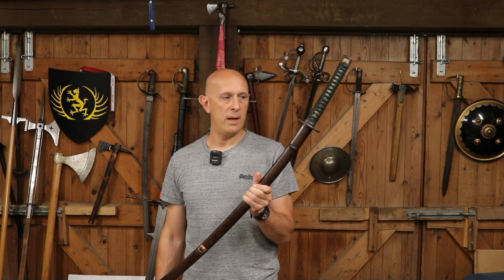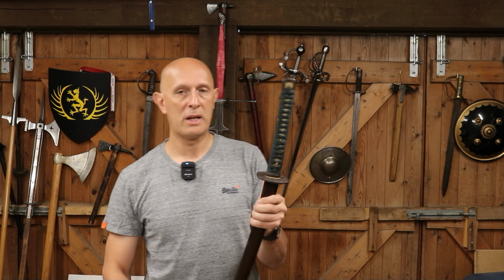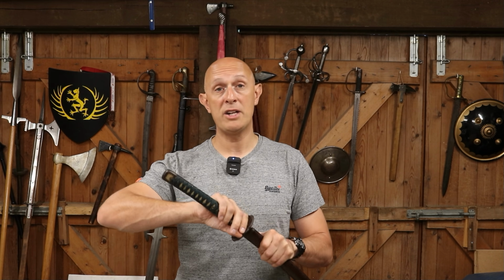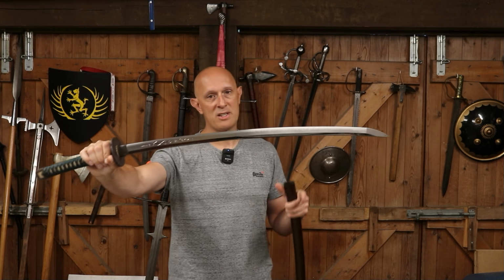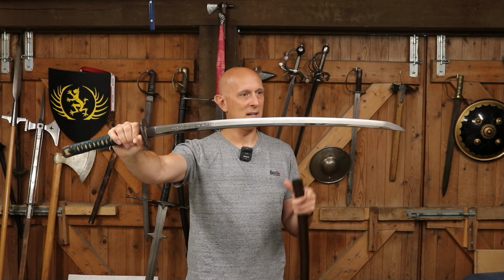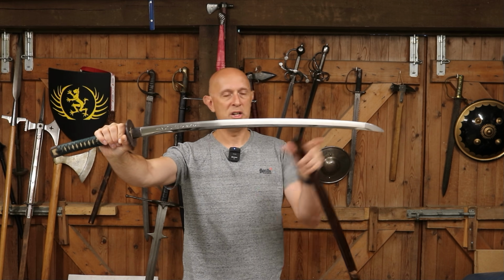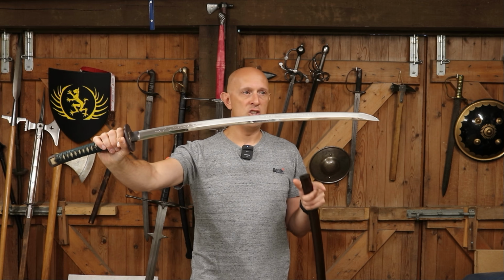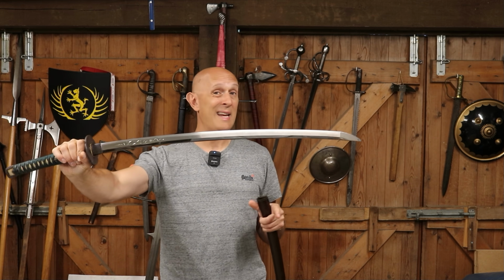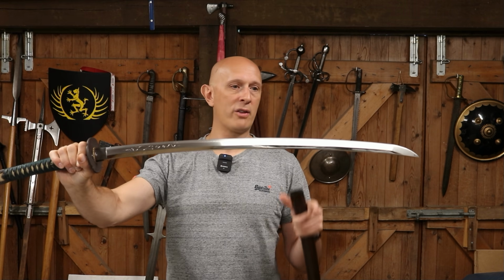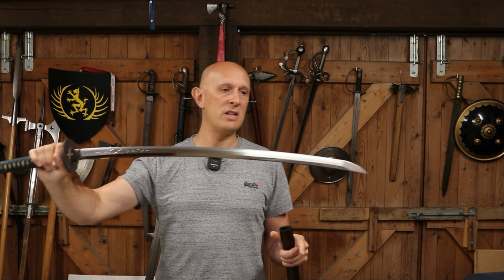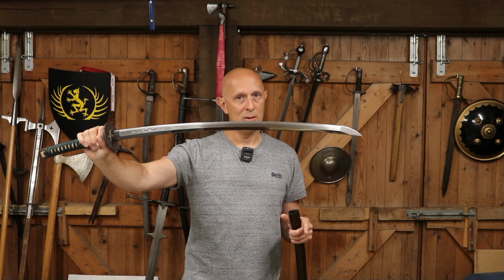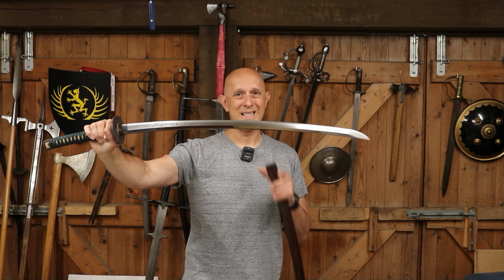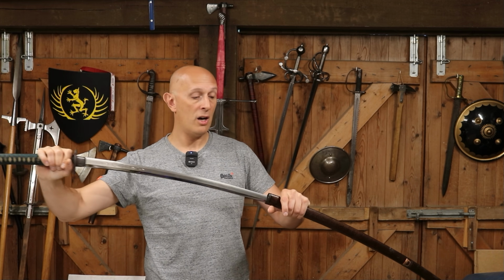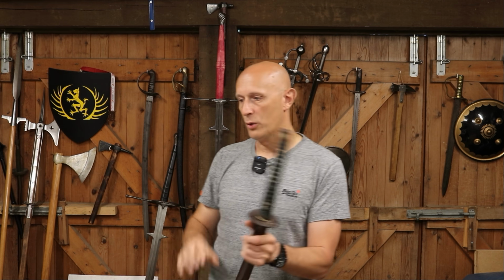However, the real outliers and the unusual ones are Japanese katana, and when we get to Japanese swords, because of their very particular method of manufacture and material as well, bear in mind they're using essentially iron sand that's turned into tamahagane in a very, very particular process, and then water quenching the edge. Basically you do end up with much harder edges on Japanese swords than any other type of sword that I'm aware of, and that's undoubtedly one of the contributing factors to their legendary status. Japanese swords are frequently around 60 Rockwell on the edge on well-made examples. So they are much harder on the edge compared to your, say, 40 in most of the rest of Asia and Europe and Africa.